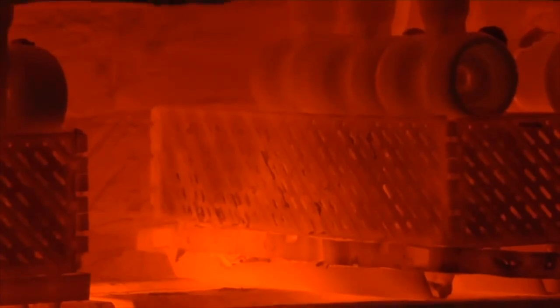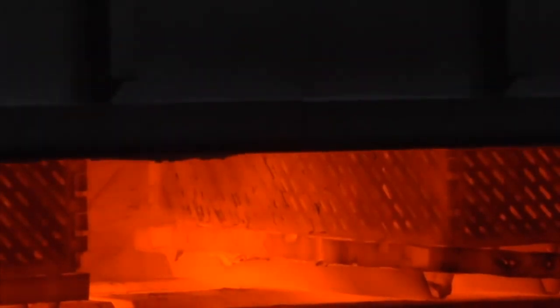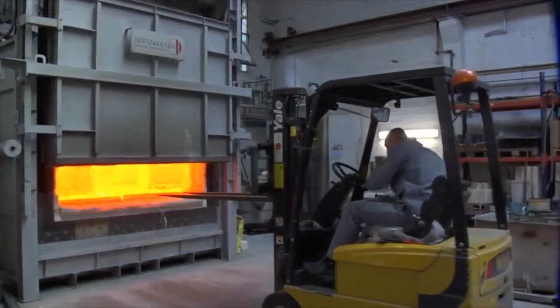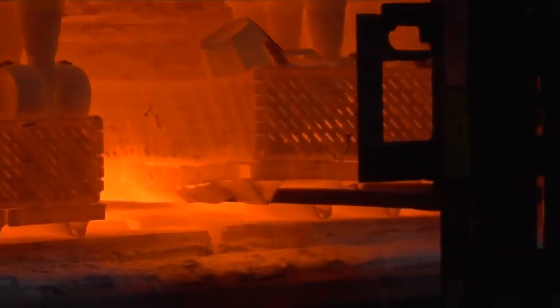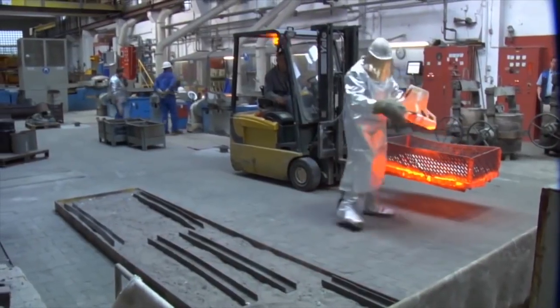The plastic models soften at 80 degrees Celsius and shrink so that tears cannot form in the ceramic shell. Finally, the 3D printed model is burnt out from the casting die in the kiln. The plastic models burn out with virtually no residue.